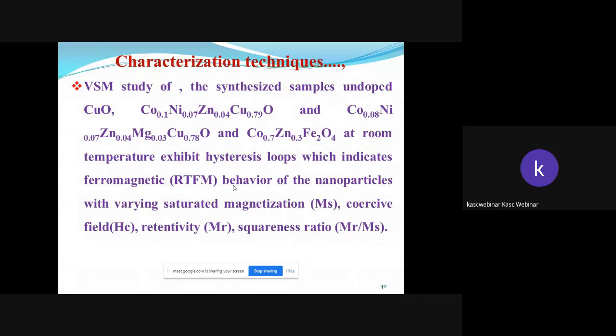VSM study, that is a vibrating sample magnetometer study, of the synthesized samples, that is doped and undoped copper oxide and doped iron oxide, at room temperature exhibits a hysteresis loop, which indicates ferromagnetic behavior of the nanoparticles with varying saturation magnetization. Coercive field is a measure of the ability of a ferromagnetic material to resist demagnetization. Retentivity, Mr, is the ability of the substance to retain magnetization. Squareness ratio, Mr by Ms, is the magnetic induction at zero magnetizing force divided by the maximum magnetic induction in a symmetric cycle of magnetization of a material.